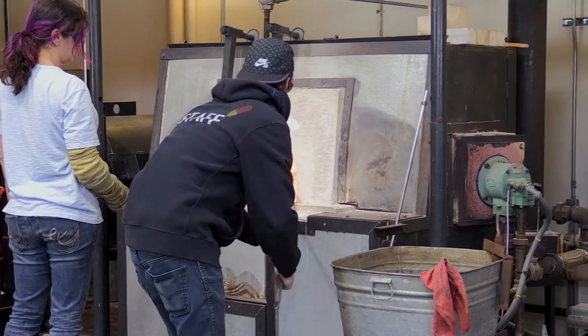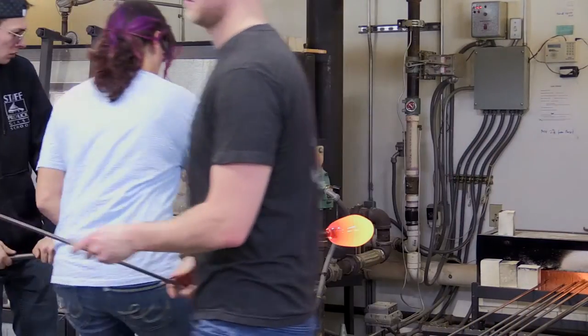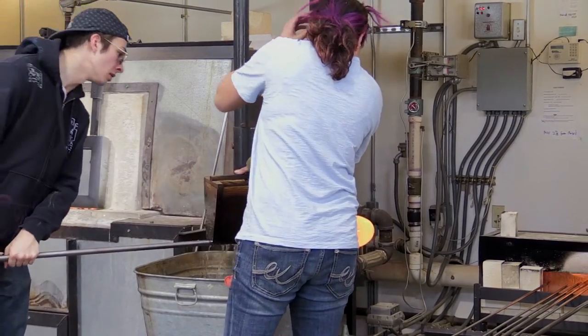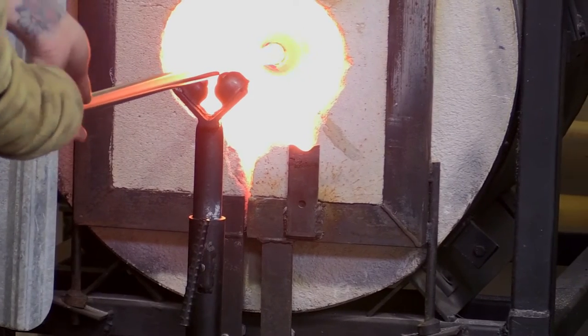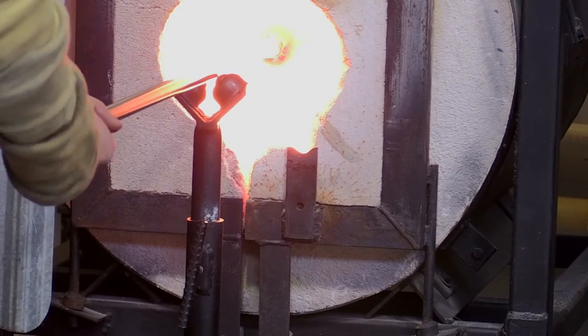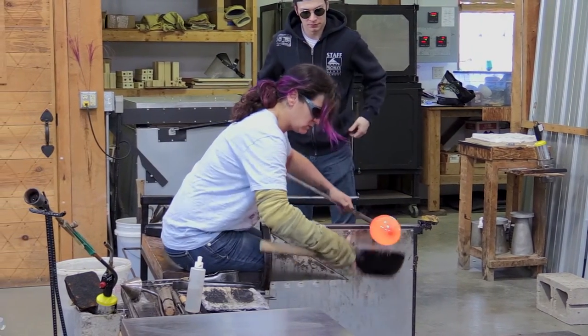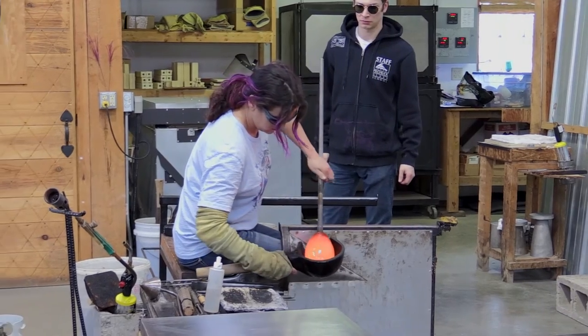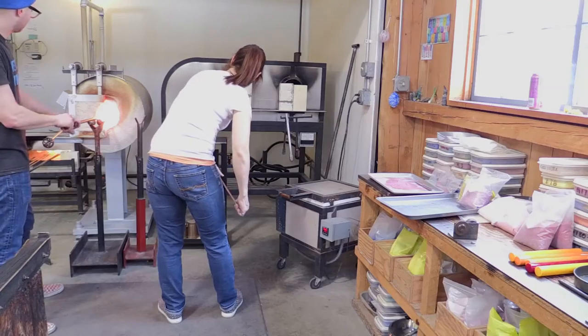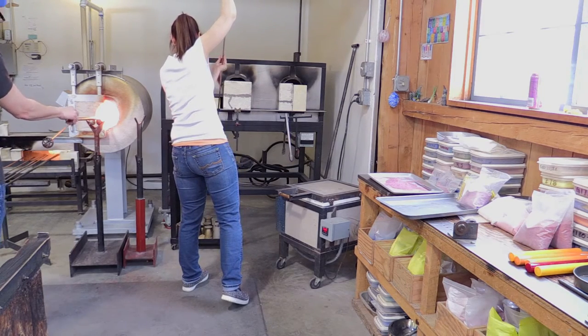Here's Orion making a bigger gather. We put layers of clear in between the layers of color — each time you pick up clear, you go back and get more frit, more color. They have to keep the pipe cool so you can touch it. And this is called the glory hole? That's a glory hole — it's for reheating. When you take the glass out, it cools, and as you touch it with tools it cools further, so you need to go back to soften it. You work on center, so you keep it turning — you're constantly turning that tube.